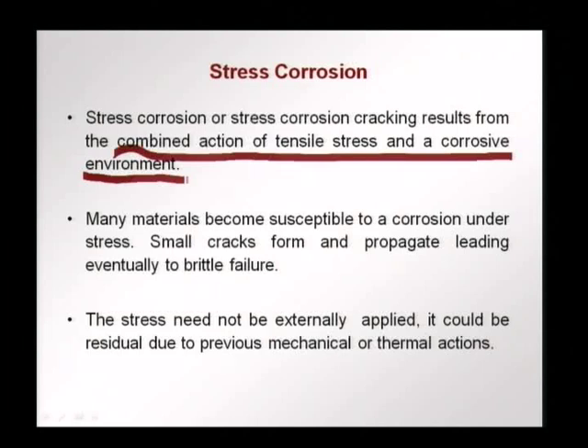Sometimes a stress or a load may not be necessary, just the residual stresses due to previous mechanical actions like strain hardening, cold working or thermal actions, thermal fatigue, cycling of temperature can provide enough stress to cause corrosion. And this is one reason we have higher corrosion possibility in strain hardened materials, because you have grains now which have higher energy, they have surfaces which have higher energy and therefore can corrode faster.